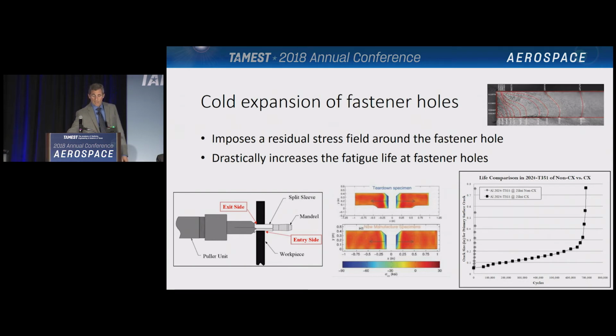So the plot on the bottom right shows crack length versus loading cycles, as an example of test data showing the difference between crack growth at a cold worked hole and at an identical hole without the cold working. So you can see that the crack at the cold worked hole, shown over here, is significantly slower than the crack at the non-cold worked hole, which looks almost vertical on the scale here.